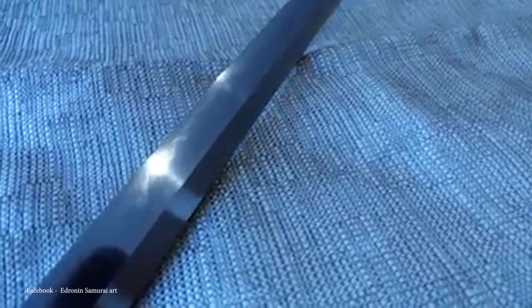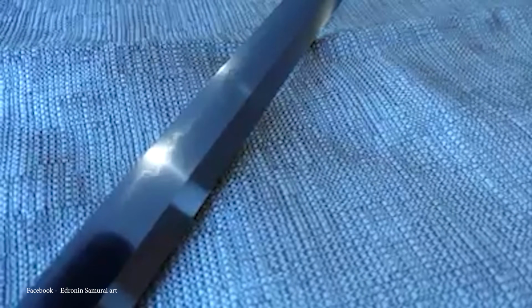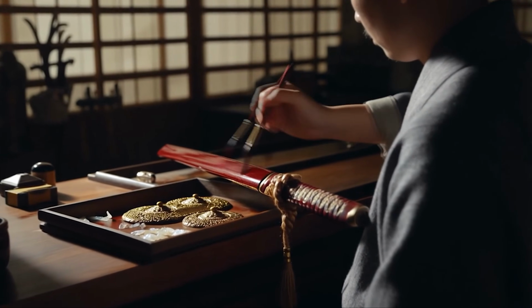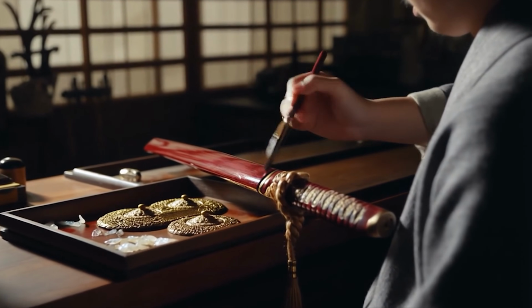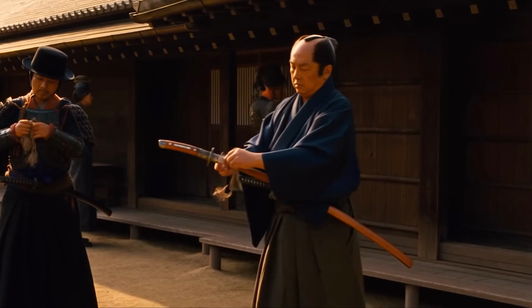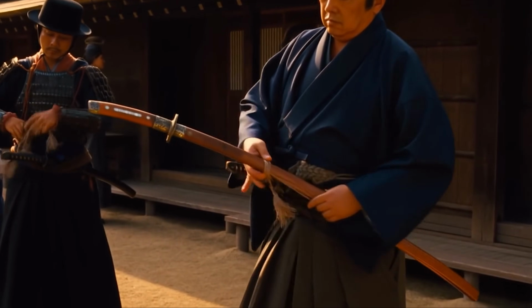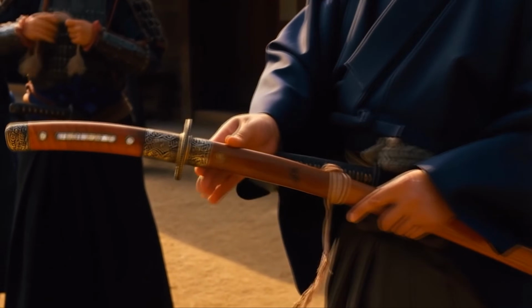The defining feature of the Tachi is its differential hardening technique, which creates a hardened steel edge and a softer spine. This is achieved by coating the spine with a thick layer of clay before quenching, slowing its cooling rate. The result is a sharp, durable edge supported by a resilient, shock-absorbing back.